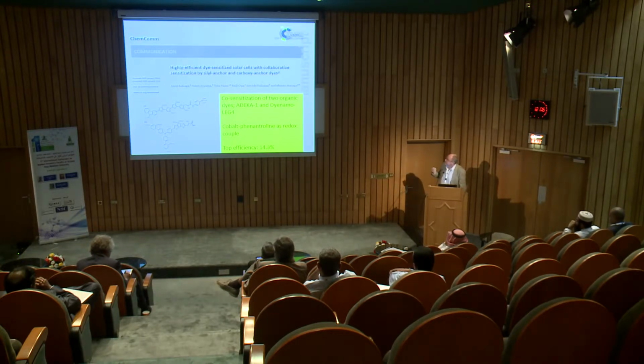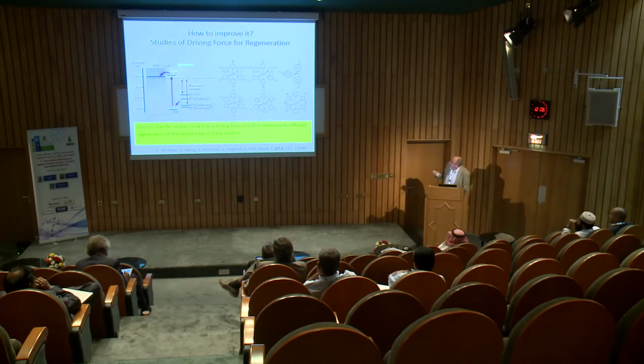Now the question is, can we still think about further improvement? And the latest direction we take comes from an understanding of what is now, with the cobalt complex, the driving force we need to regenerate the dye. I said it was 0.7 with iodide, and here we can nicely study what we need in terms of potential driving force to the dye by tuning the different cobalt complexes here, which we did from Uppsala in collaboration with EPFL. And I think we made about 12 different cobalt complexes with different redox potentials.